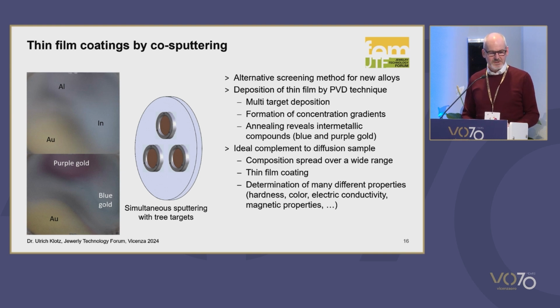So the picture here is showing a glass plate, maybe like 20 times 20 centimeter. And then we used sputtering technique to deposit alloying elements on this glass plate. And we used 3 different alloying elements: aluminium, indium, and gold. So they are arranged in a triangle. And so they're sputtering material from different sides. So we get mixtures of alloying elements on this glass plate.